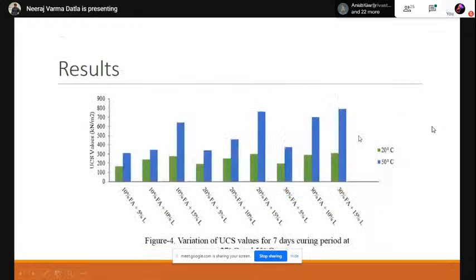And this is the comparison between the ambient temperature and elevated temperature. If you check these, when we compare the curing at normal temperature, the elevated temperature is showing higher values. This is due to the acceleration of dissolution of silica and alumina at higher temperatures, mainly for fly ash content.